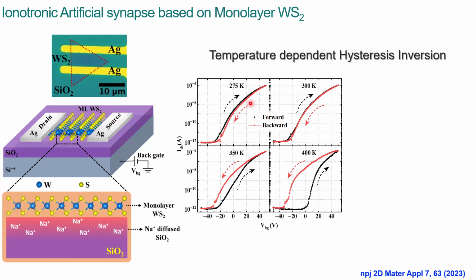So if we see this graph, it demonstrates that at nearly room temperature, less than room temperature, you will see a clockwise hysteresis behavior. And this clockwise hysteresis, there is some hysteresis from back to forth and forth to back. This small hysteresis is because of trapping. SiO2 is a 3D material, and when you have a 2D material on the 3D material it has some dangling bonds. These dangling bonds can hold some electrons during the trace back. And this hysteresis is coming because of this trapping.